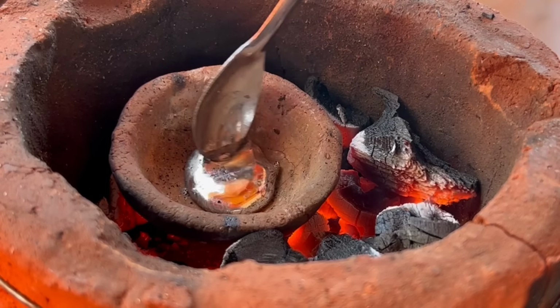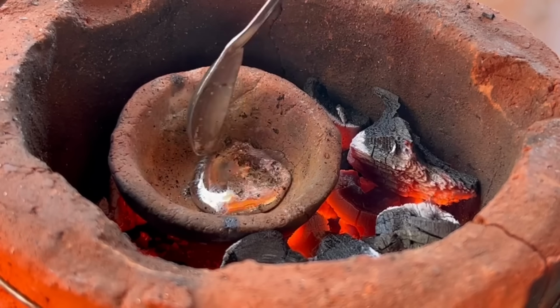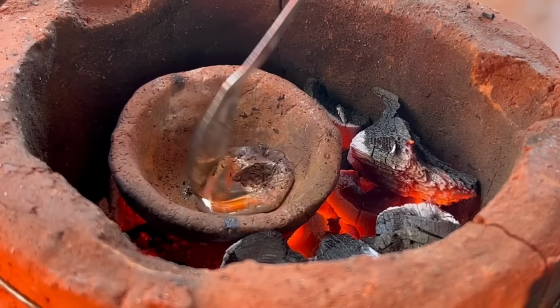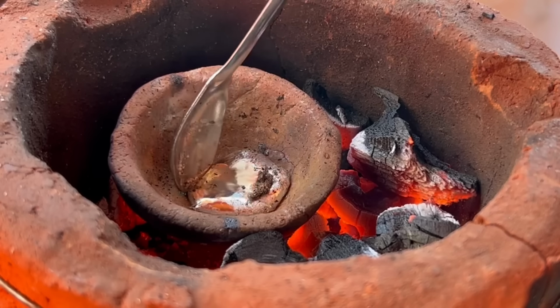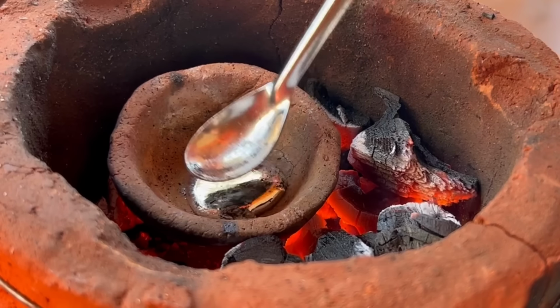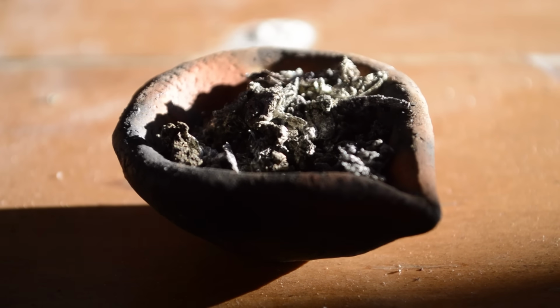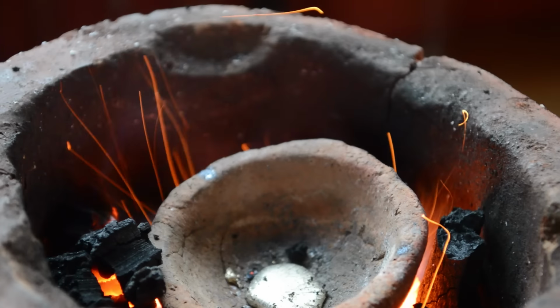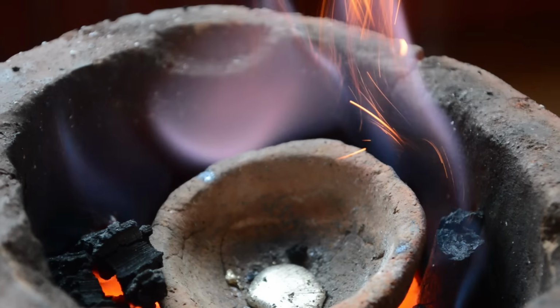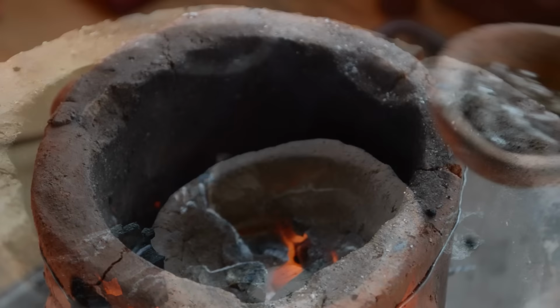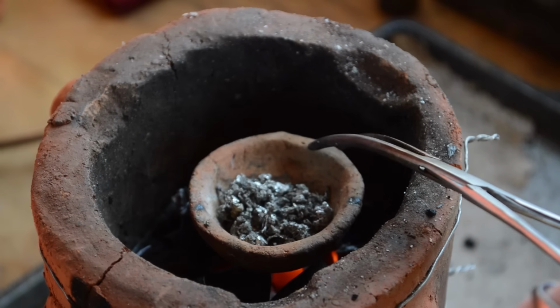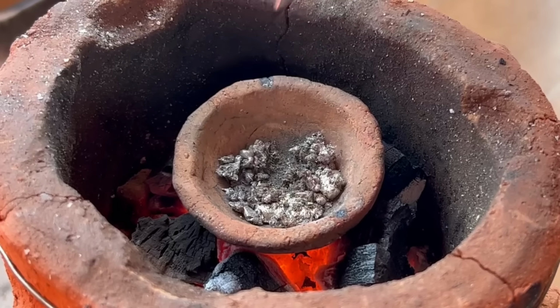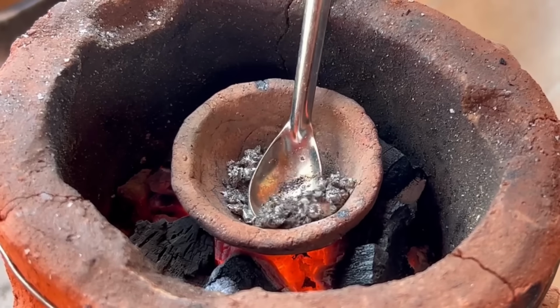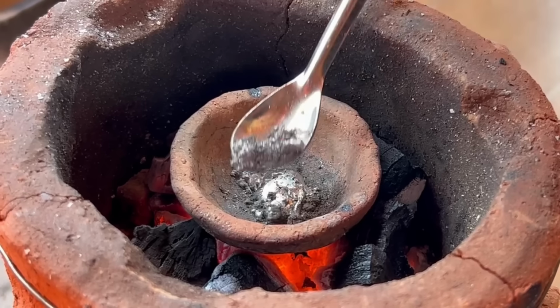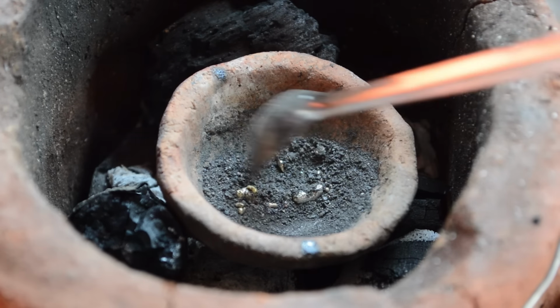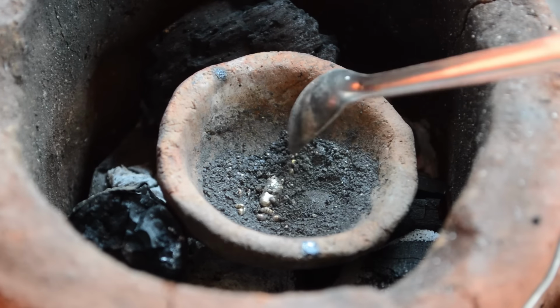In his own words, Jabir says the reason calcination was invented was so that the corrupting and defiling sulfurity may be abolished by fire. To calcine this metal, I have to continuously stir the molten metal and separate off the slag as it firms, saving it in another crucible. Slowly, the bead of molten metal becomes smaller and smaller as more slag is removed. Once I've separated a good deal of slag, I throw it all back into the crucible and calcine it further. This separates the metal from the oxides it's mixed with and produces a grayer, more powdery slag. I repeat this process again and again until instead of slag we're left with just a dark gray powder mixed with beads of metal.